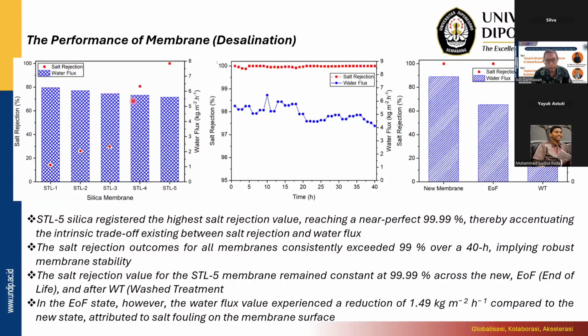And we are trying to test this for the long-term application, up to 40 hours. And up to 40 hours, the salt rejection is still around 100%. So we can see